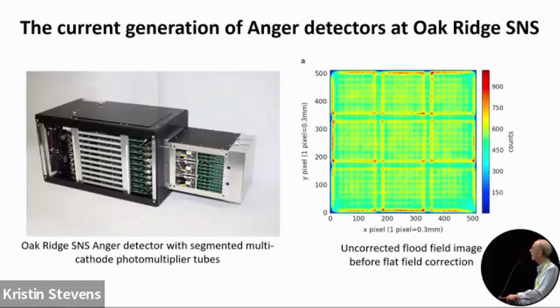Currently, the current generation of Anger detectors at Oak Ridge, one of them is shown here. This is the front end of the detector where the scintillator is. Now there's a 3x3 array of roughly 2-inch square tubes again, but these are now segmented multi-cathode photomultiplier tubes. There's an 8x8 array, so for each of these multi-cathodes, the spacing is about 6 millimeters. So now the resolution is 1.2 millimeters, so it keeps getting better. There are close to 100 of these detectors currently operating at the SNS.